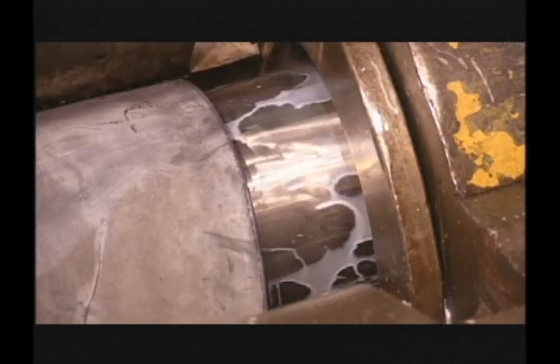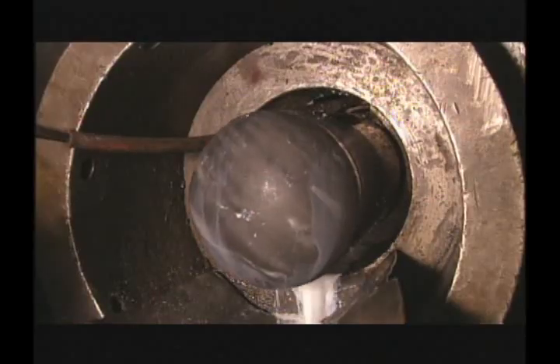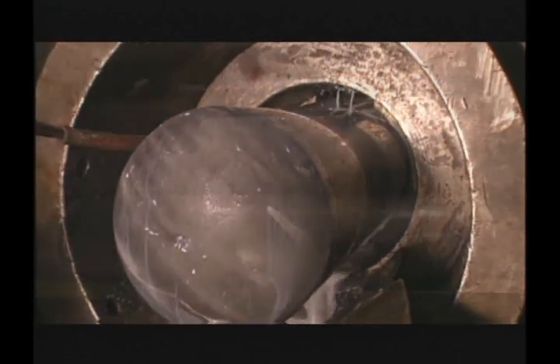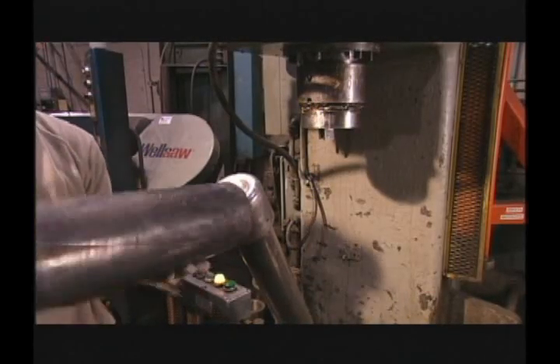first-draw cups and secondary cups are processed through the final draw. This press utilizes up to 250 tons of force. Since draw rates are relatively quick, a flood-type coolant is used to prevent overheating. Most scuba cylinders are produced in three draws,